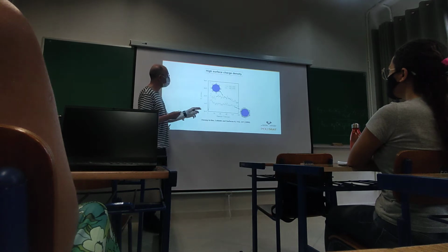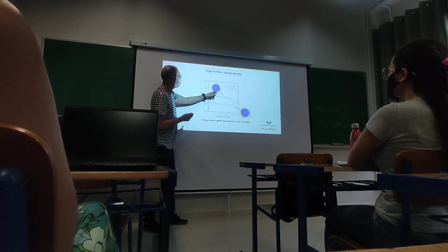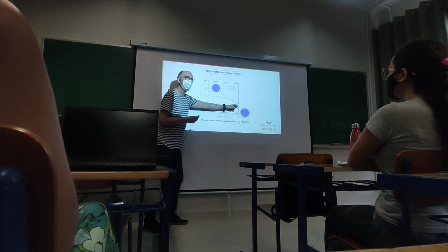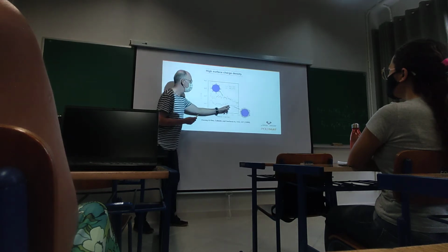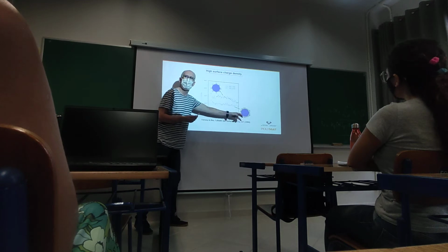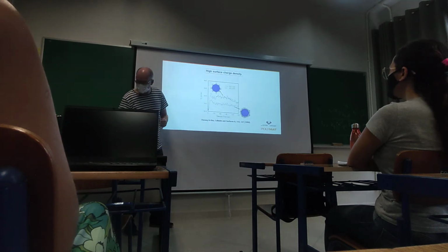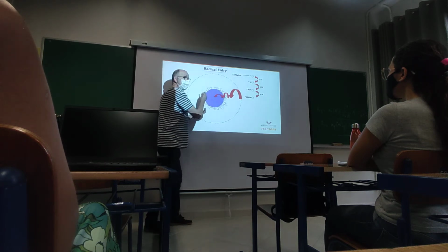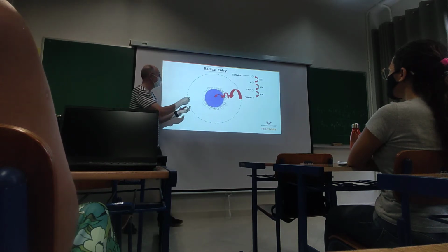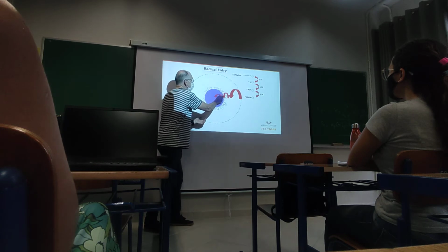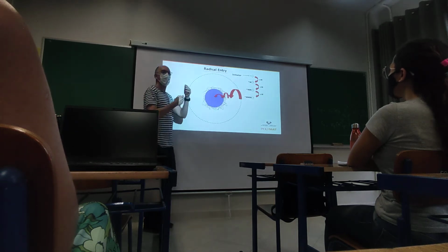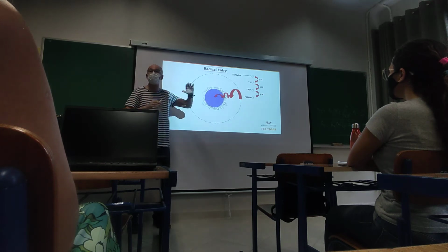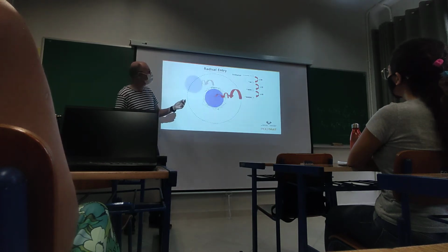So what they observed is that when the charge in the surface was lower, the polymerization rate was higher than when the charge was high. So basically this is implying that this resistance changed from one case to the other, and when there is a lot of resistance here, the entry of radicals was lower, and therefore the average concentration of radicals was lower and the polymerization rate was lower. This is what they found.